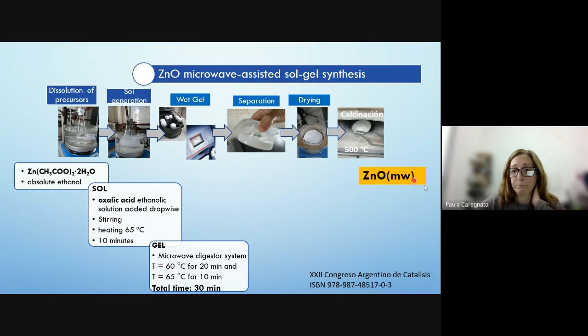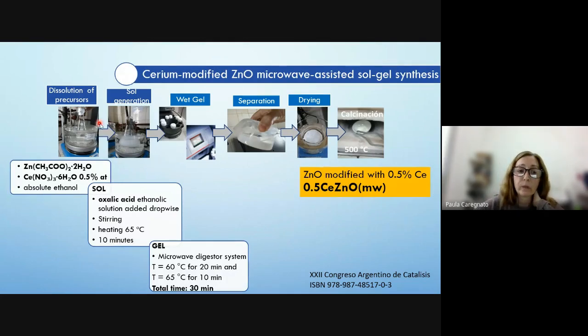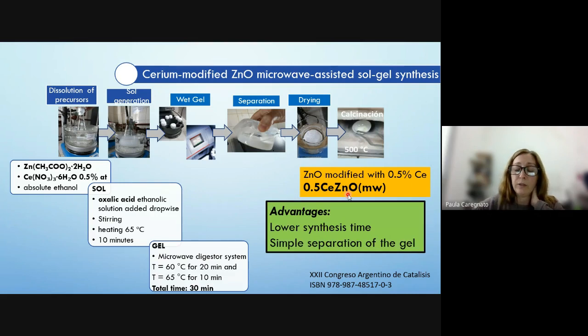The cerium-modified zinc oxide by microwave-assisted Sol-Gel synthesis was obtained by incorporating cerium nitrate into the precursors, but now in a quantity of 0.5 nominal atomic percent. The following steps were the same as the procedure without cerium. The material here is named 0.5 cerium zinc oxide microwave. The advantages of this synthesis were the lower synthesis time and the simple separation of the gel.